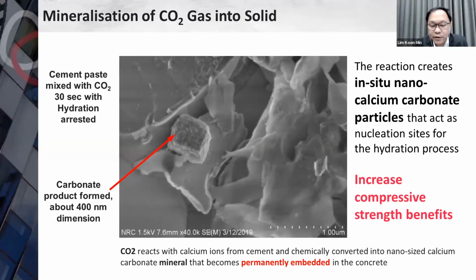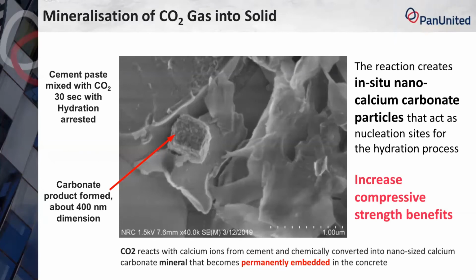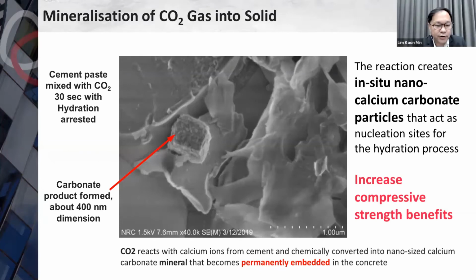Now let us take a closer look. So from the video, in short, when you inject liquid CO2 during concrete production, this CO2 reacts with the calcium ions from cement and is chemically converted into a nano-sized calcium carbonate mineral, and becomes permanently embedded in the concrete. And why do I really stress this permanently embedded? That means that this CO2 in the concrete, at the end of life of the building, when we demolish this building, will not escape back to the atmosphere.